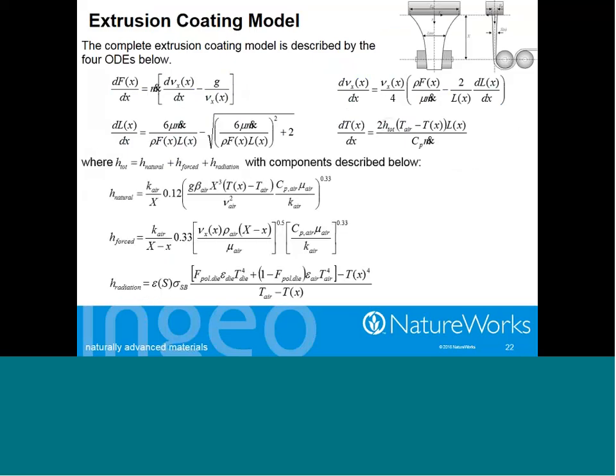The next slide is, I guess, my attempt to show you how sophisticated we are here. We're not going to go through the math, even if we had time. But the extrusion process is an extremely complicated process. There's a lot of things changing as a function of time. And in order for us to develop products related to this extrusion process, we need to have an in-depth understanding of the process and what's going on. And so there's a number of equations here. This dF/dx has to do with the force applied as we're pulling the extrudate out of the die. That dL/dx term has to do with the narrowing of the melt curtain as it comes out of the die. The dV/dx has to do with the distance and the velocity of the polymer melt.